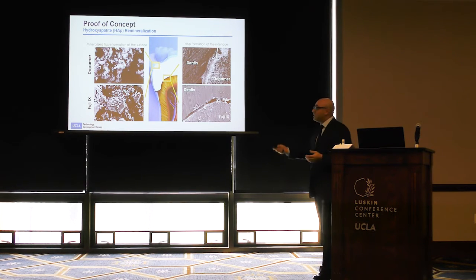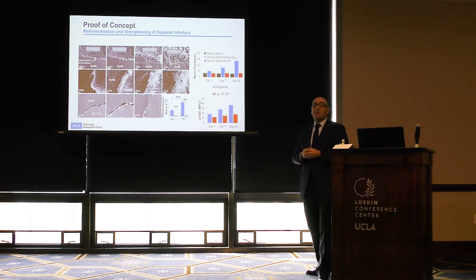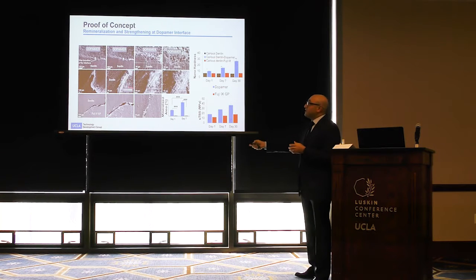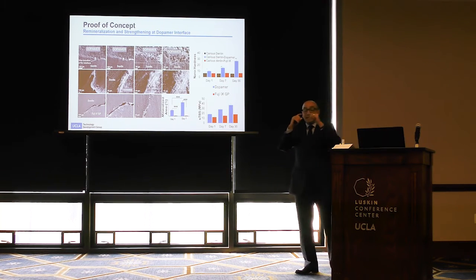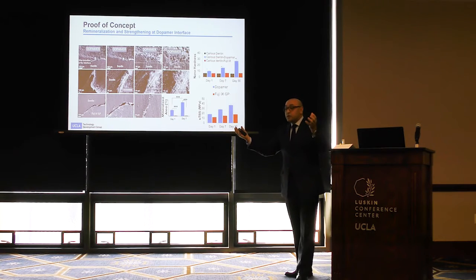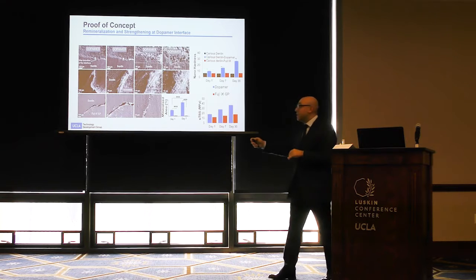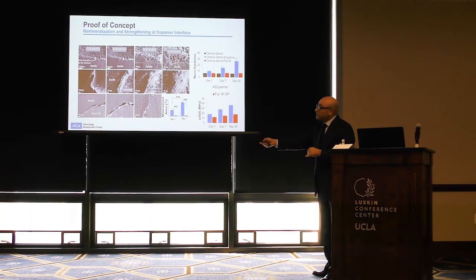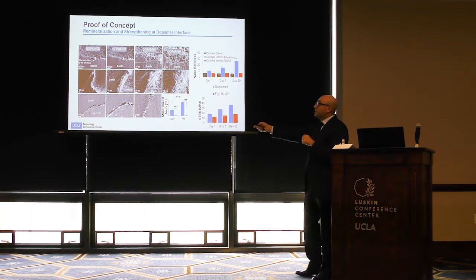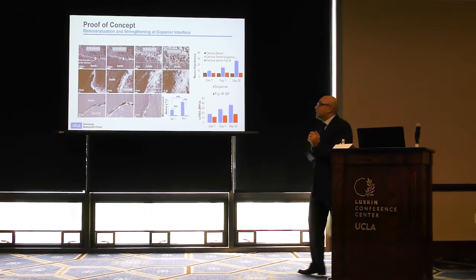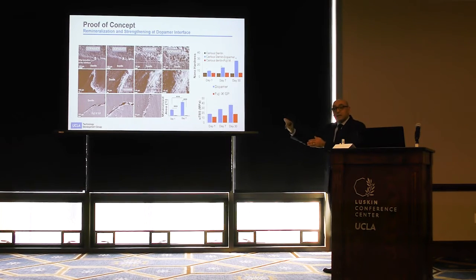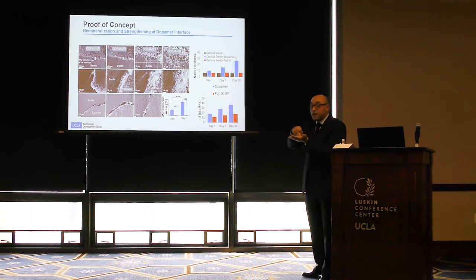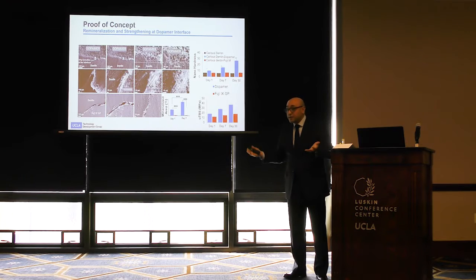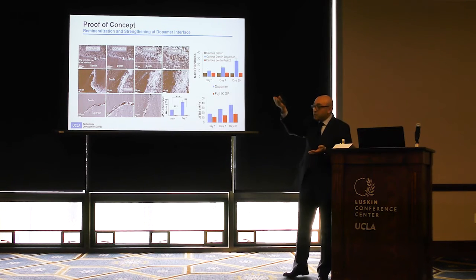Gap, microleakage, recurrent decay, versus our material making a beautiful calcium phosphate layer, remineralization, so we don't have any recurrent decay problem. We did another set of studies. We actually utilized dentin that has a little bit of decay. When the dentin or your tooth structure has decay, it has lower mechanical properties. So we filled that decayed part with our Dopamer technology. We immersed the material in artificial saliva, and after different time intervals, we looked at the nano-hardness, the mechanical properties of that interface, to see if our material is really remineralizing the interface. There should be an increase in the mechanical properties.